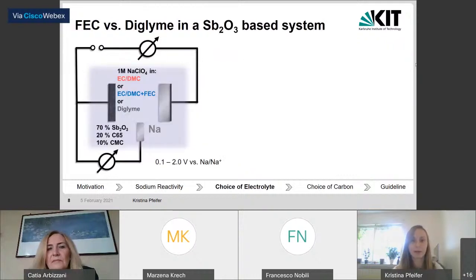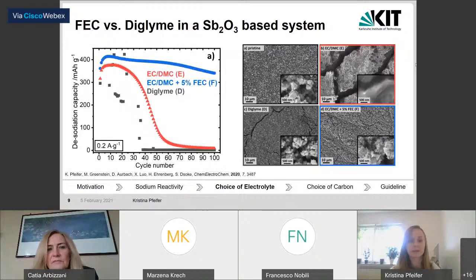We did this by using a material with a very complex electrochemical behavior, antimony oxide. By cycling this material in different electrolytes, we were able to investigate the influence of the electrolytes on the sodium metal and on the working electrode. What you see here is mainly that in the case of FEC, we get a very good stable electrochemical behavior, whereas when we use diglyme, we get very irregular values of the capacity, even if the electrode doesn't look so much affected. This is because diglyme can dissolve the active material. So the sodium metal is stable, but the active material is affected.